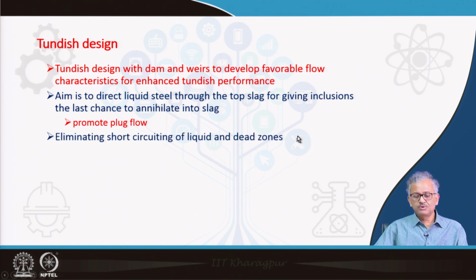Then eliminate the short circuiting of liquid and the dead zones. If some liquid, after pouring from the teeming ladle, comes directly to the exit stream, then it is called short circuiting, because some of the fluid elements can be arrested in the reactor in the form of a CSTR, continuously stirred tank reactor. Basically, a reactor is a combination of plug flow reactor, continuous stirred reactor and the dead zone also. I will come to that, but eliminating short circuiting of the liquid and the dead zone is very important. If liquid comes directly from the teeming ladle to the exit, that is called short circuiting. In that case, liquid will leave with a very high superheat. Okay. So we have to stop that, and also this liquid does not get any chance for inclusion removal.